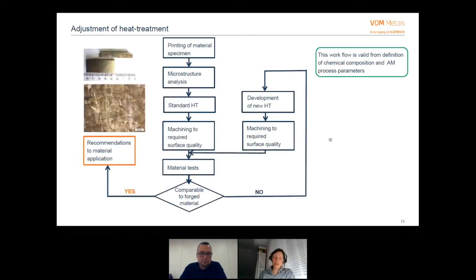We discussed a lot about surface. If we have one chemical composition which should work well during or after AM, and we also choose the process parameters that also work well for this chemical composition, we usually start working with microstructure analysis, and start with standard heat treatment. Standard heat treatment shouldn't always fit to printed parts in comparison to raw parts. And after some evaluation, if it fits, we go to material testing, compare it with forged material, and if it answers yes, we go to application.